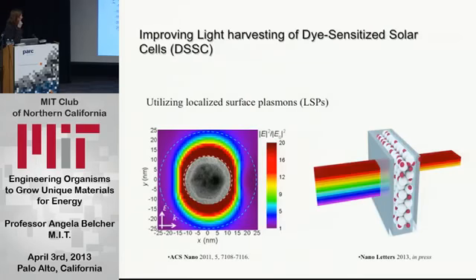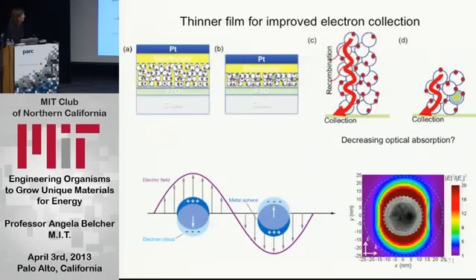We also said, well, what can we do about increasing light harvesting in the system? And so we looked at improving light harvesting with metal nanoparticles of gold and silver. And the idea was, if you start to think about electron collection again, you can make the film thinner, which will give you more collection efficiency for your electrons, but then it decreases your absorption because you don't have as many dye molecules. And so we said, well, can you increase your absorption by putting metal nanoparticles, gold and silver, into the system to increase your absorption and to broaden out the spectrum of your solar cell.